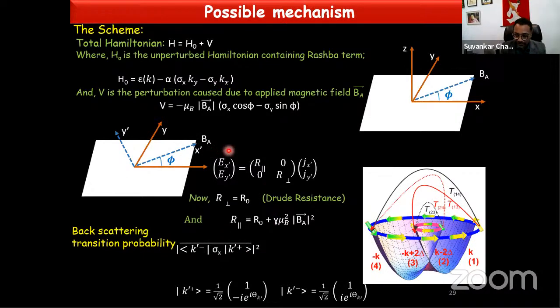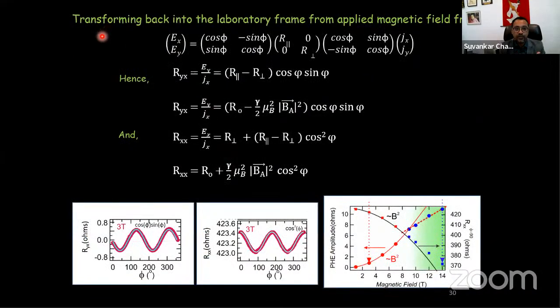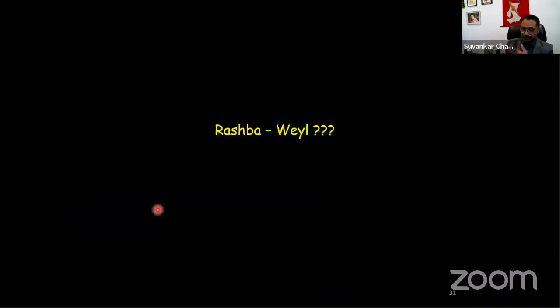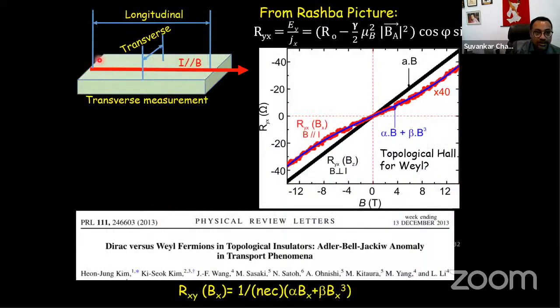So we could calculate this, and we make a transformation back to the laboratory frame, and we can see that the longitudinal resistance has a cos square phi dependence, which we have already seen, and your planar Hall has a cos phi sin phi dependence, which we have already seen. So we could basically understand that at least at low field, this can be explained by using Rashba type physics.